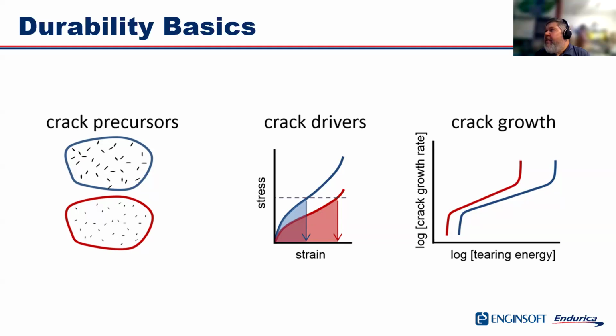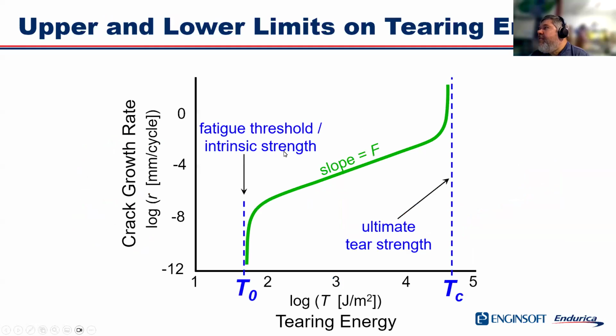And then finally, the last thing that we worry about in general when we're thinking about durability is crack growth behavior. So typically what we might do is to make a plot of the rate of growth of a crack as a function of the energy input to the crack. And if you put enough energy in, the material will spontaneously grow cracks without any cyclic load, just in a single stroke. At lower tearing energies, you'll get fatigue crack growth. And then if the tearing energy is sufficiently small, then that's what we're talking about when we say a fatigue threshold, right? Is what's the minimum energy that it takes to grow a crack. So these are kind of the basic ingredients for any fatigue analysis.